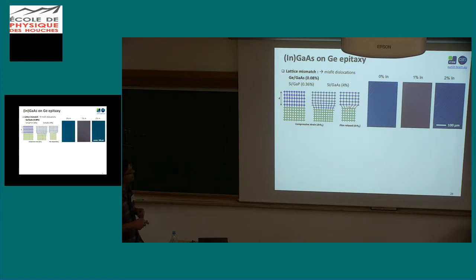And you can see that if you grow only gallium arsenide on germanium, you have a bunch of defects. If you add 1% indium, it will be perfectly okay. And then again, if you put in too much, it's not okay. The reason why it gets better is because indium is just below gallium in the periodic table. The atom is slightly bigger, and so by putting 1 atom every 150, you will increase slightly the lattice parameter of this indium gallium arsenide, and germanium, and you end up with this.